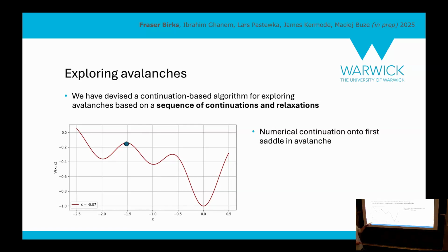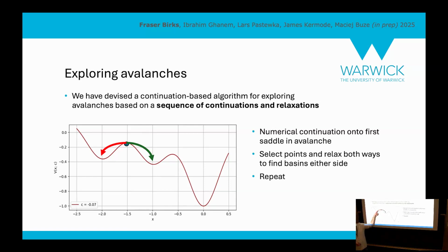So we're on the saddle point, right? And because, as I showed you earlier for the irreversible bond case, it's mostly the case that the next event that happens will not be this saddle colliding with this minimum, in these amorphous carbon systems. So what we do is we just relax off this saddle point. We minimize off the saddle point. And by doing so, we can find the adjacent minima on either side, right?